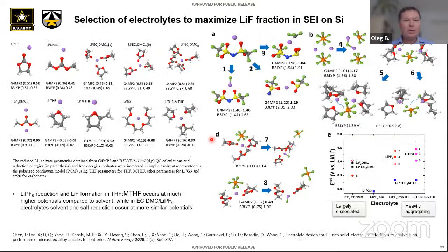I want to make one example based upon joint work with Chunsheng Wang's group, where they came up with a very innovative idea of how to stabilize a silicon anode. They said that instead of having oxide interfaces or carbonate SEI, which bind to silicon pretty strongly, a very lithium fluoride-rich interface would allow silicon to slide and essentially have a framework of lithium fluoride in which silicon would flow in and out as it lithiates. And as it lithiates, it changes its volume by a factor of 3. So as it lithiates inside the lamellas of the SEI, it will have much better performance.